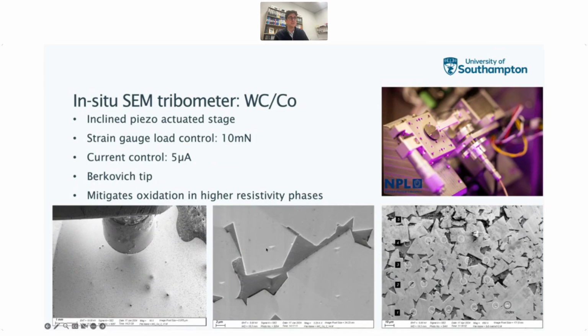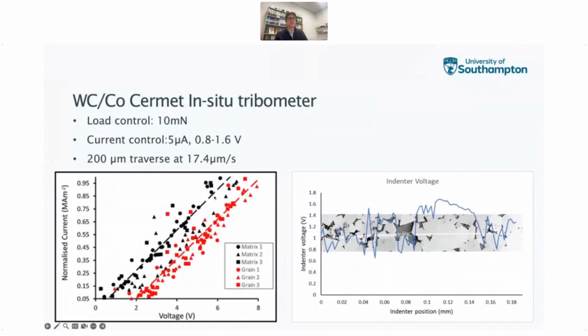We could control which phases we were going into with a 5 microamp current, and we could actually start getting some measurements that weren't compromised by this oxidation behavior, and that was quite useful then. So we could start mapping out the different phases. We could target the different phases, and then start to see that if we normalize for the contact area that we were putting them into, we can get discrimination between the tungsten carbide, which has a higher resistivity, versus the cobalt, which is a little bit lower. So that's useful. Well, you can then start to attempt traverses in that mode, and we've done that here.